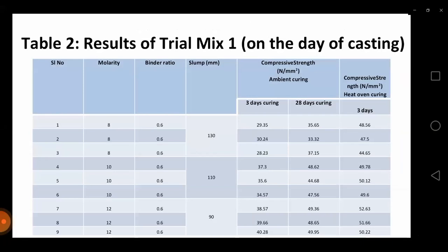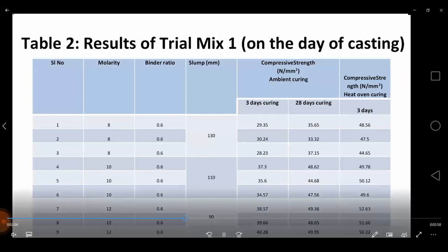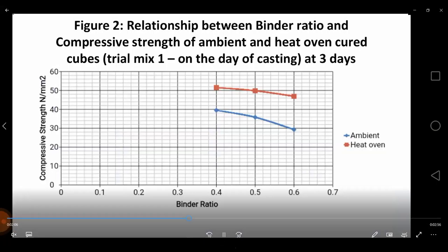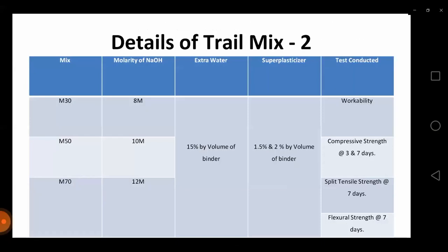And these are the results of the same trial mix when we add the sodium hydroxide and sodium silicate on the day of casting. And this shows the relation between the compressive strength and the binder ratio again for the ambient and the oven cured cubes at 3 days. So here the oven cured samples are giving more strength than the ambient cubes. So these are the details of the trial mix considered extra, with superplasticizer, which is 1.5% and 2% by volume of the binder.